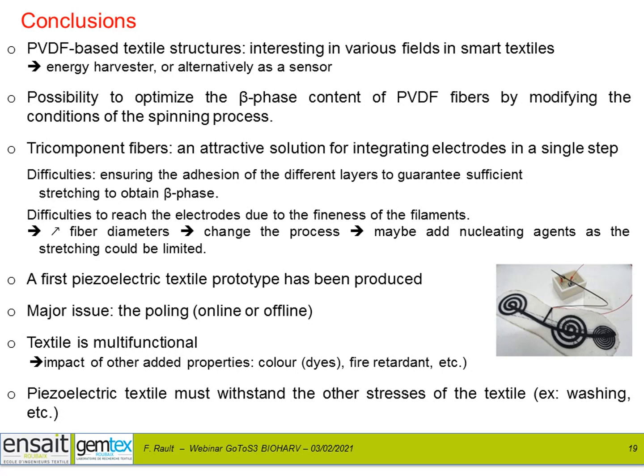For example, there are still some difficulties to ensure the adhesion of the different layers to guarantee sufficient stretching to obtain beta phase. It is also difficult to reach the electrodes due to the fineness of the filaments. So one solution could be to increase the fiber diameter, but it will be necessary to change the process. In consequence, maybe it could be interesting to add nucleating agents to promote the beta phase content due to the limiting drawing ratio, which can be obtained with a new process.